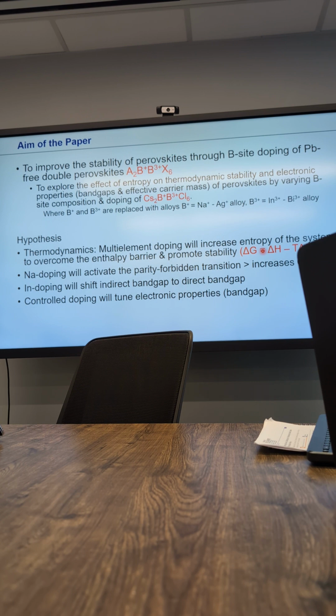And they are saying that we want to create as much configurational disorder in the system because of this alloying, that the entropy effect surpasses the formation enthalpy, and then makes your delta G negative, which makes your system more feasible or more stable. And so they used computational tools to do this, which I'll get to shortly.